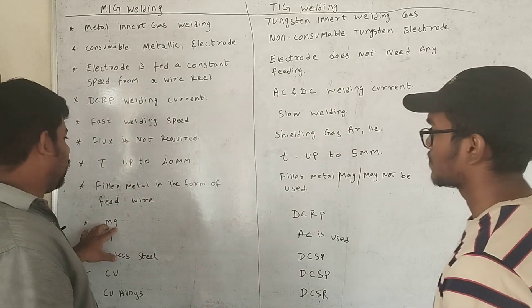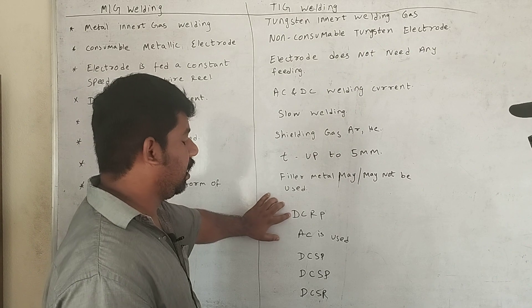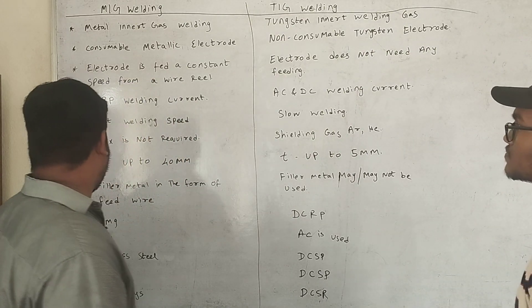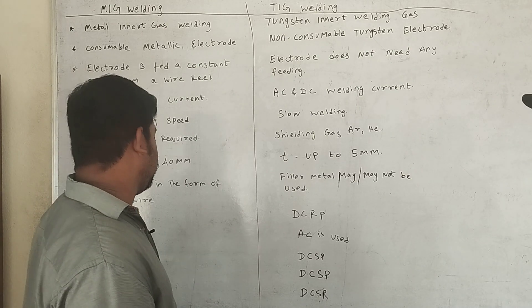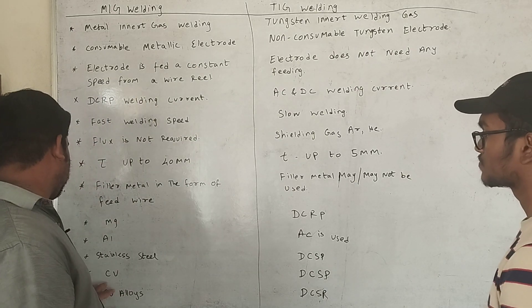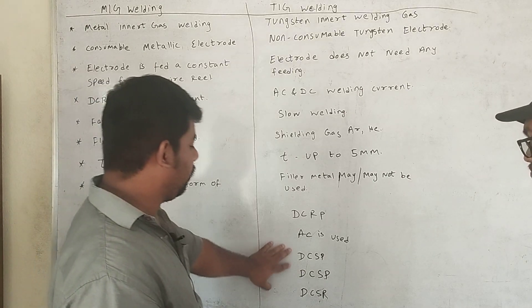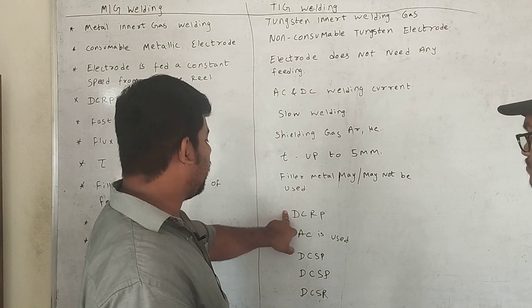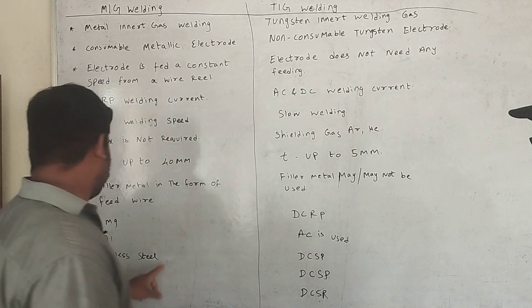For magnesium, direct current reverse polarity is used. For aluminum, AC current is used. Stainless steel, copper, and copper alloys use direct current straight polarity, while magnesium uses direct current reverse polarity.